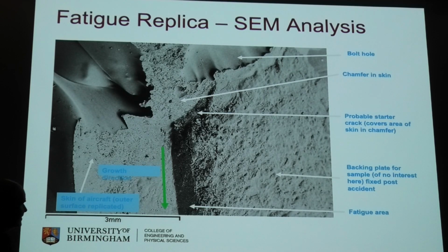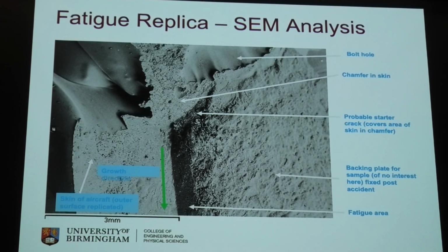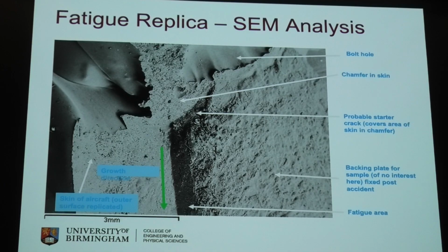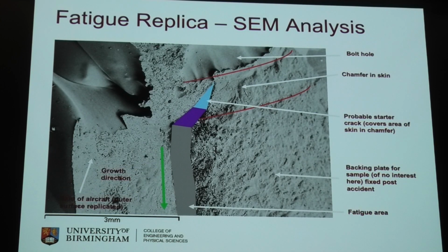And then there's the chamfer in the skin that comes down from that, and the starter crack is sitting under that bolt hole. At the end of the starter crack, the crack changes direction into the direction of maximum stress. So they created this crack. It sat entirely under the chamfered head. They couldn't see it, but it caused failure. And it's about 1.6 millimetres long when I stuck it on the microscope. So we can find that detail, which wasn't reported in the initial report, but we found it on the stuff ever since. And that sits roughly where it is.